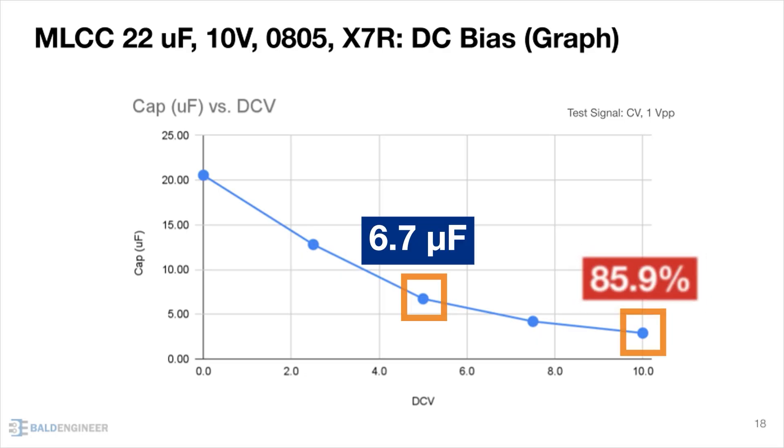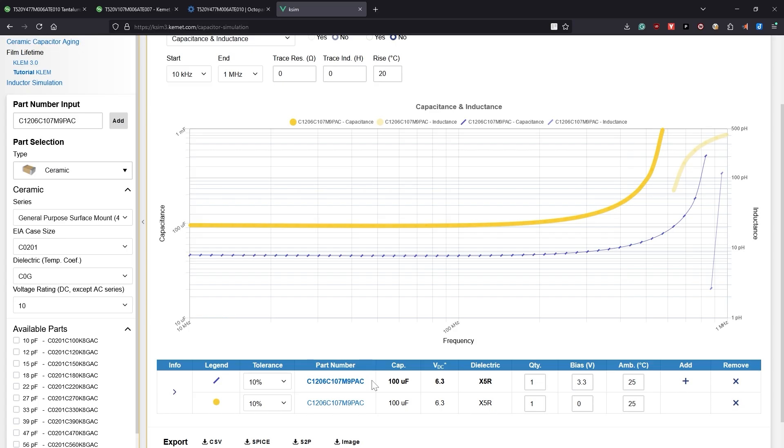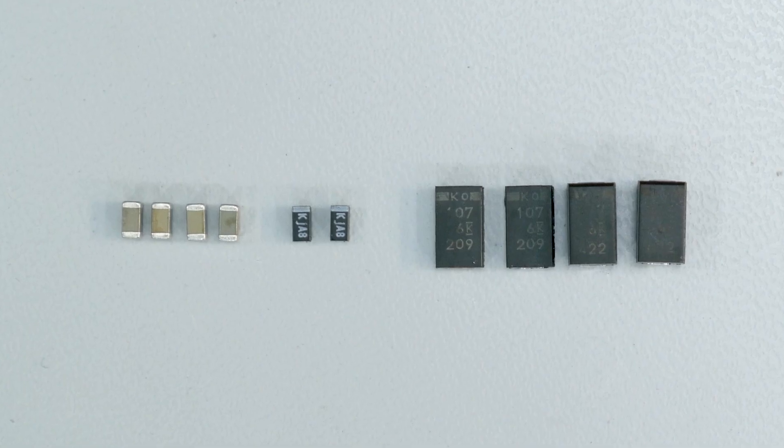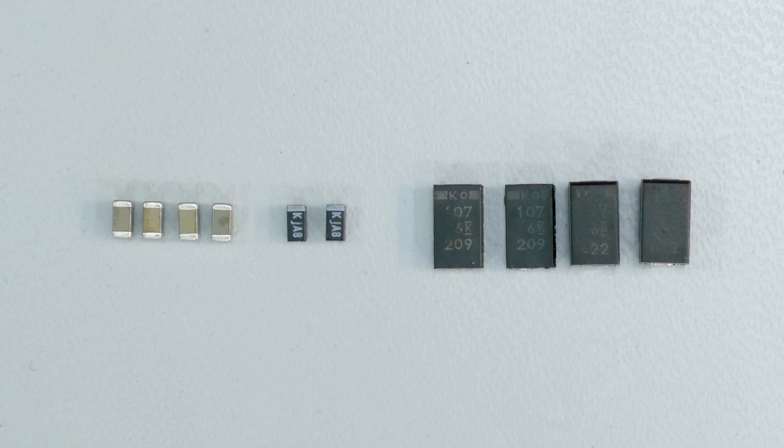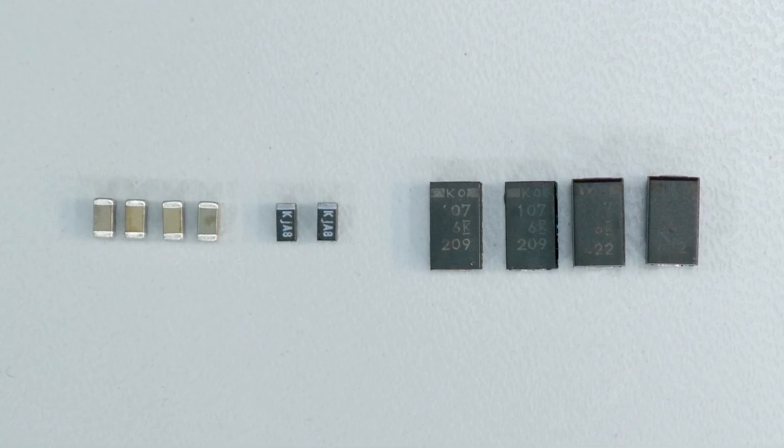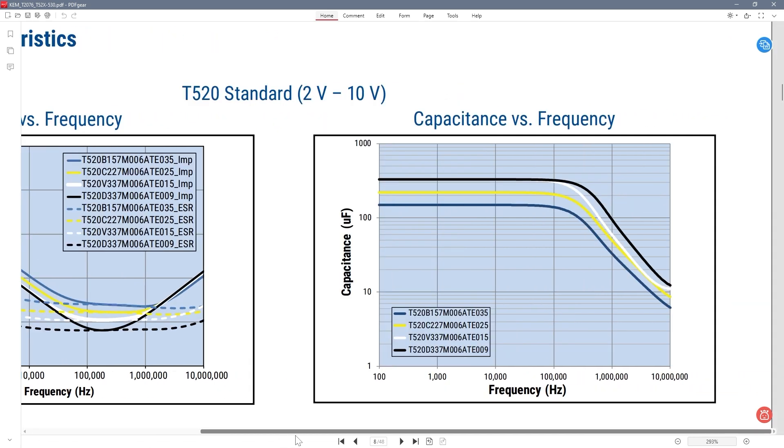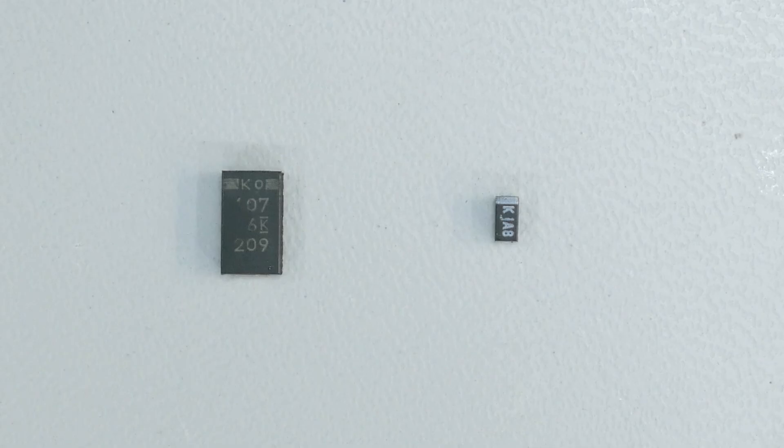In conclusion, can you replace MLCCs with KO caps or polymer electrolytic capacitors? Well, I say yes. Sometimes you can. But you should consider a few things. Always consider that multi-layer ceramic capacitors have a DC bias effect. You need to see what their effective capacitance will be in your application. Polymer footprints are more readily available in case sizes larger than MLCCs. So, if you know you want to experiment, consider larger or multi-pad solutions for easier swaps. Also for polymers, watch the switching frequency and their response. In general, they respond to higher frequencies as their rated ESR goes down.